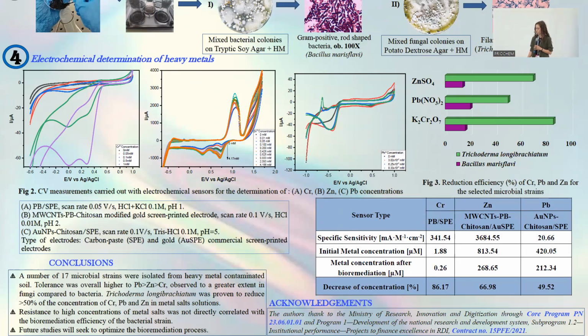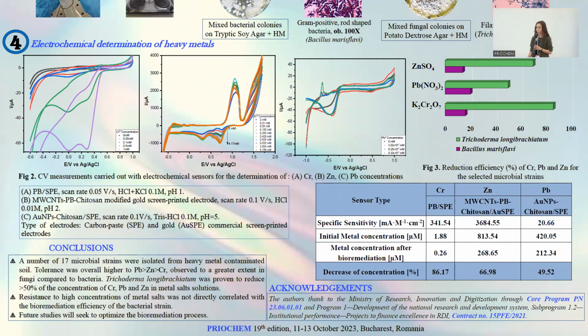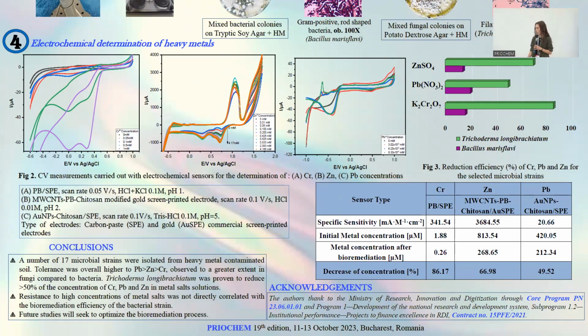For zinc detection, multi-wall carbon nanotubes were used in pair with Prussian blue and chitosan. And for lead detection, excuse me, was used a polymeric matrix containing gold nanoparticles and chitosan.